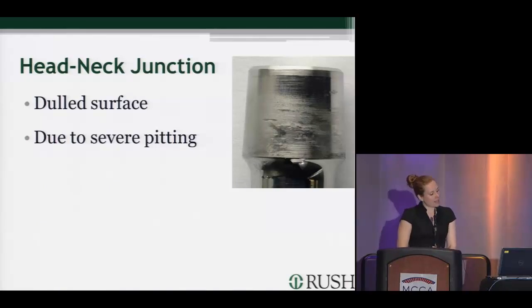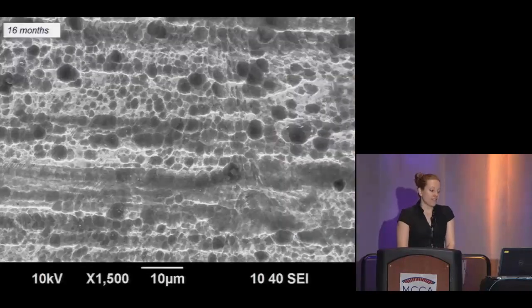At the head-neck junction, damage appeared as a dulled surface, and this dulled appearance was due to severe pitting. However, the severe pitting wasn't observed until these devices were placed in an SEM analysis and observed under very high magnification. Here you can see the severe micro-pitting corrosion.